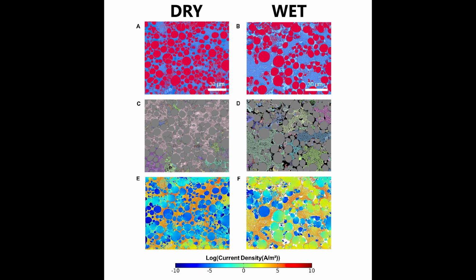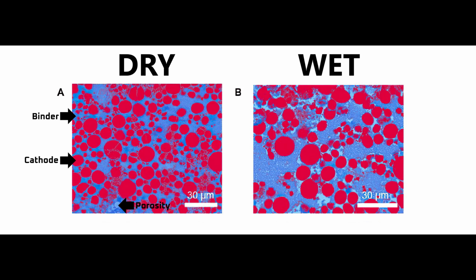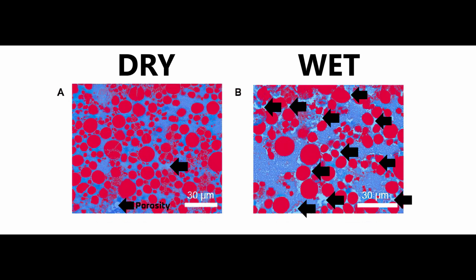Next, let's check out the test results of the proposed dry-coated cathode versus a wet-coated cathode. The images on screen are colorized cross-sections of cathode material. On the left are Zhang et al.'s proposed dry-coated cathode design, and on the right are a comparable wet-coated cathode design. Images A and B show cathode particles in red, the carbon binder matrix in dark blue, and pores in light blue. As you can see, there's less porosity in image A, indicating better physical connectivity.